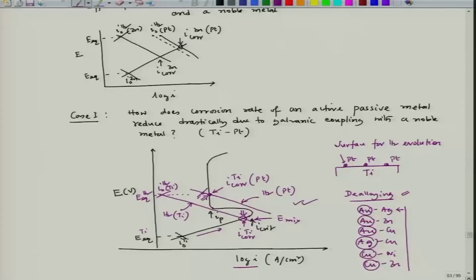So this is one such phenomenon, but there could be a situation where even if it is an active-passive metal, because of the noble metal galvanic coupling, there could still be an increase in corrosion rate, even after having this active-passive transition in that particular metal.